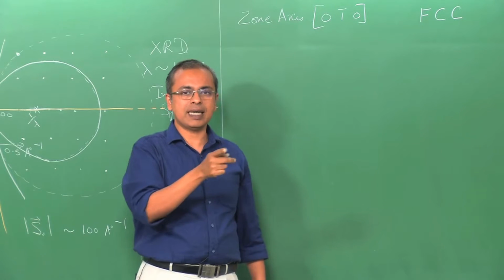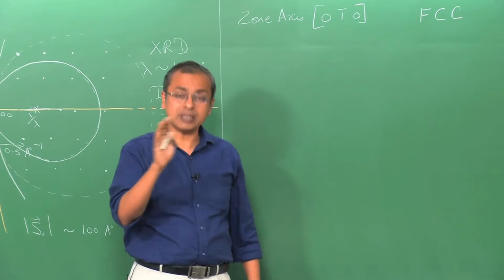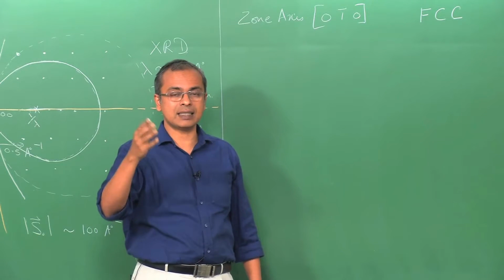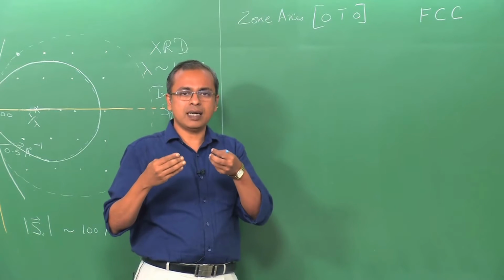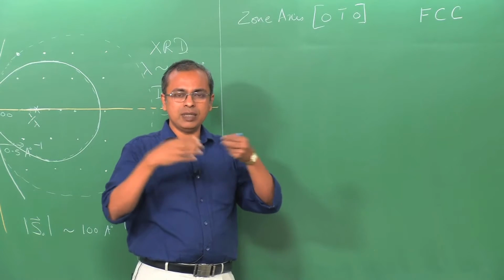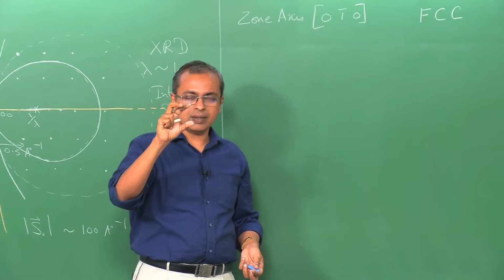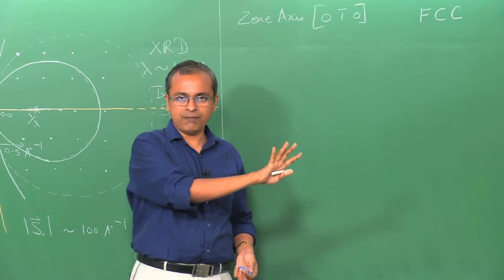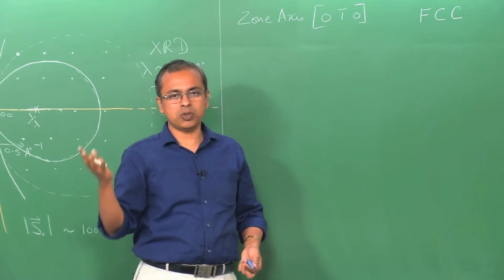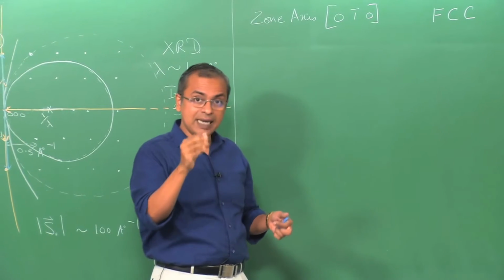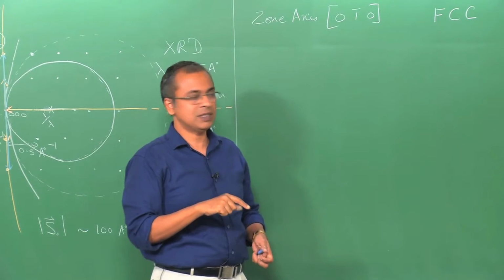Another set of points gets cancelled when you have a body centered cubic or face centered structure; you have some additional cancellations going on. A simple cubic structure in this case will give you the superset of points that you can get, a subset of those points is what you will see in face centered cubic, and another subset is what you will see in body centered cubic. So, we will do it for simple cubic, then we will highlight those points which are now valid for FCC.